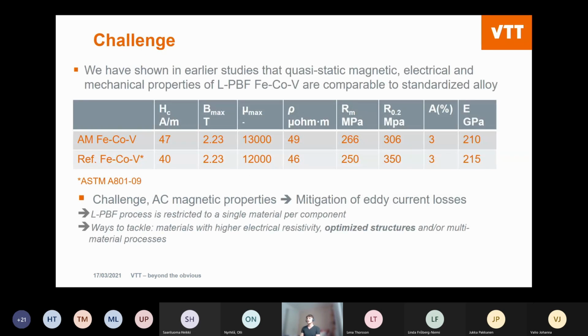In the first work we did with the iron cobalt, also alloyed with vanadium as a minor alloying element, we were able to reach comparable properties, mechanical and magnetic, compared to the laminated, so the standard material that you use today. Here you can see some of the key properties, but the challenge that remained was the eddy current losses that were also mentioned earlier in the previous presentation. Lamination is applied in conventional manufacturing to prevent the eddy current losses, and this we don't have in additive manufacturing, which is a challenge that we've tried to tackle in this SOMA project also.